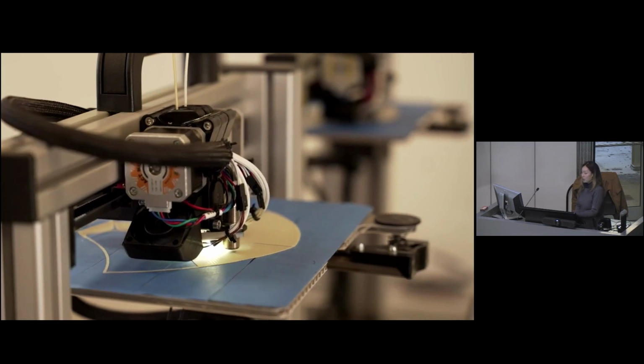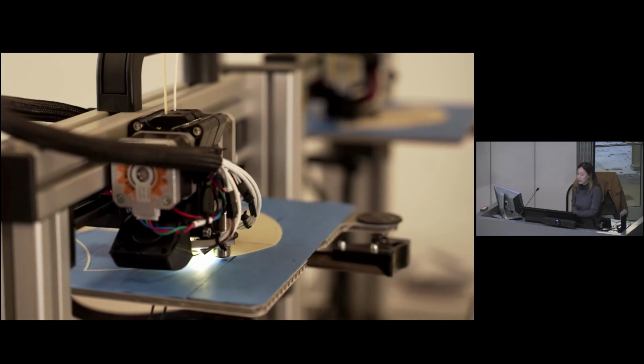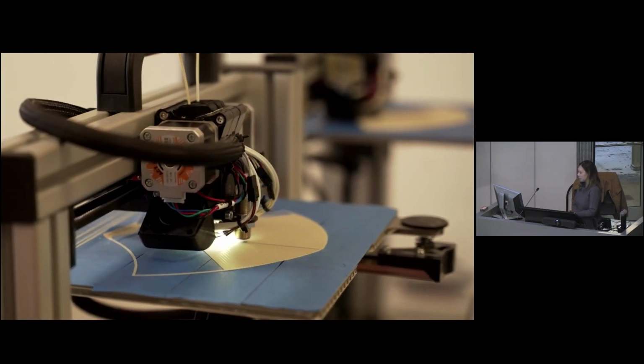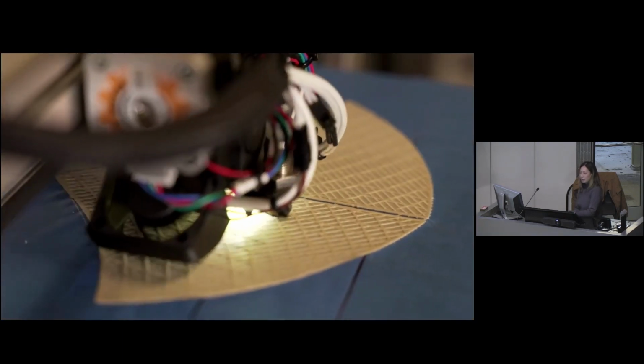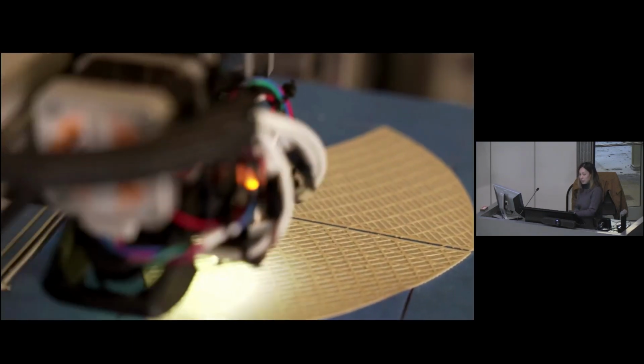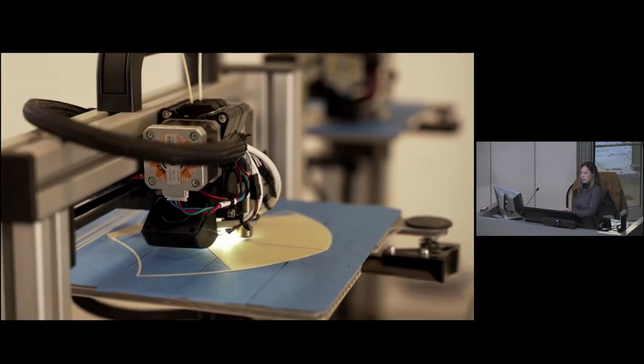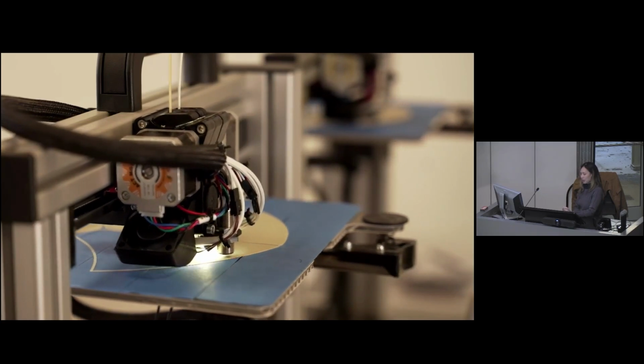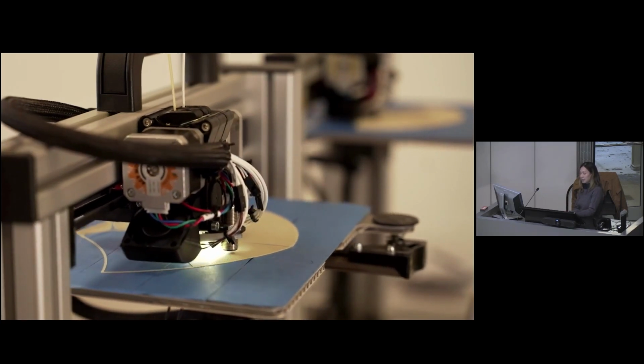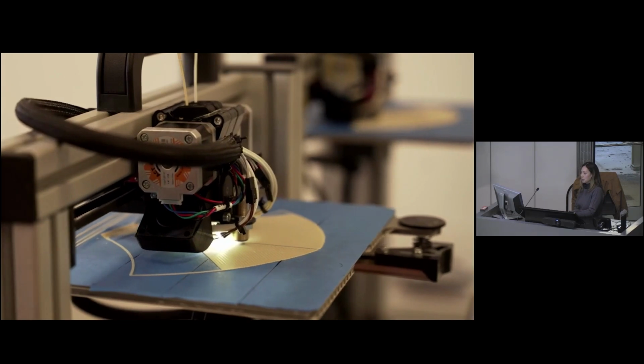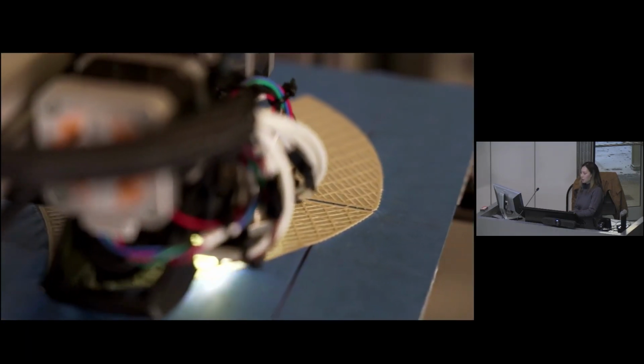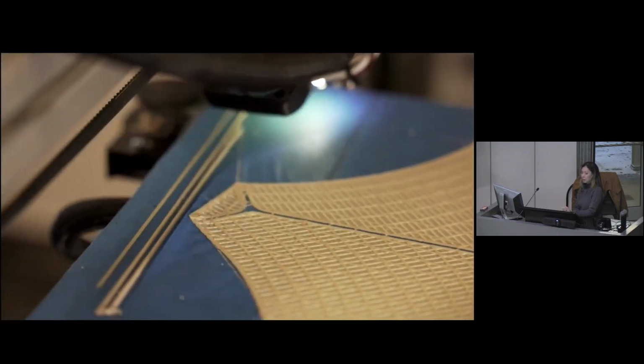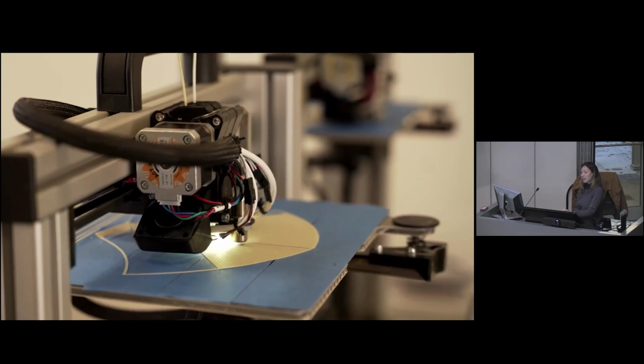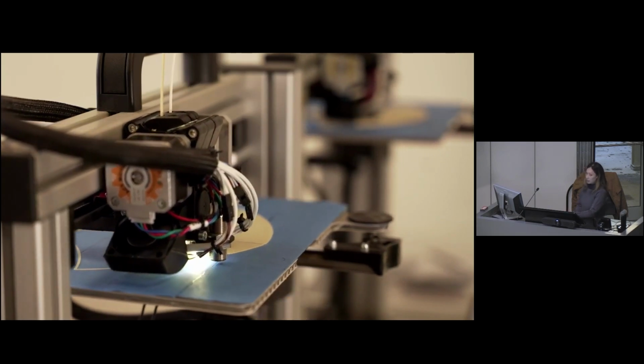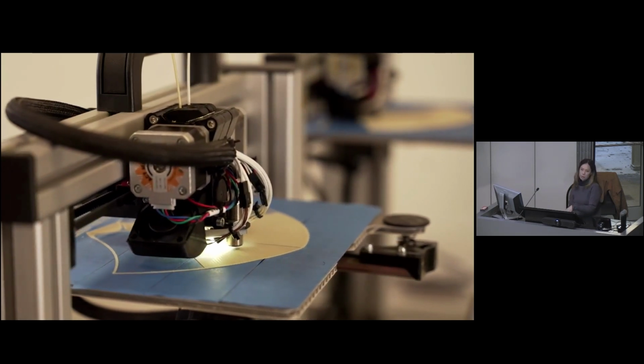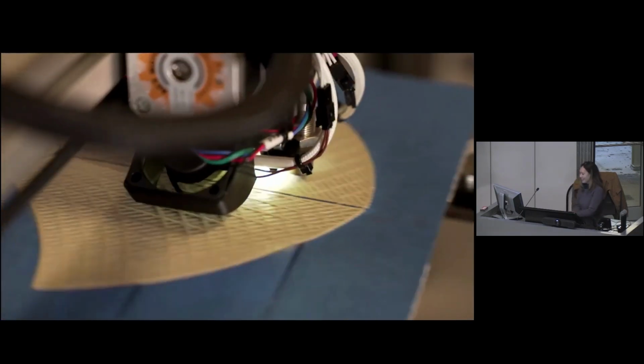And then with the assurance of our extensive testing, we rented a total of 4 3D printing machines to fabricate almost 450 shading elements. Because of that very efficient mesostructure and the fact that it's all flat, each element only took 20 minutes to produce on average. And so the entire process of 3D printing that facade took 17 days and used less than 6 kilograms of materials. And the printers were not working 24 hours a day.